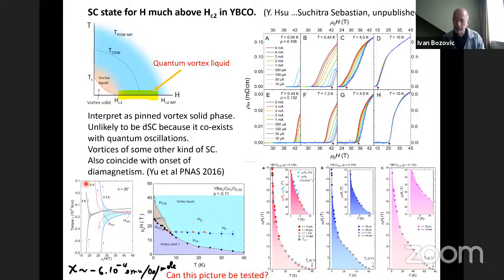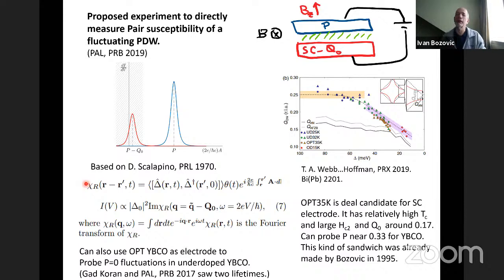The other thing is actually a question, and it may be a hard one. To me, you know, I try to keep my eye on the ball. To me, the question of high TC superconductivity is TC. Why is TC so high, and why does it depend in the way it does on the doping? So, in the RVB picture that you started from, on the underdoped side, it's really like Bose condensation, BEC. And you didn't say that explicitly, but from what else you have said, the pair density wave disappears on the overdoped side, it goes to Fermi liquid, then most people would say on the overdoped side, it should then become a conventional BCS.